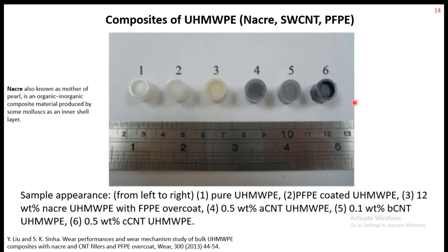Some of our works have also been represented here. For example, these specimens we prepared: pure UHMWPE, then UHMWPE with PFPE coating, which is perfluoropolyether, then 12% nacre UHMWPE and some percentages of CNT. These tests were conducted on a pin on disc apparatus, so these specimens acted as the pin, with a disc of stainless steel, sliding in bovine serum as the lubricant.